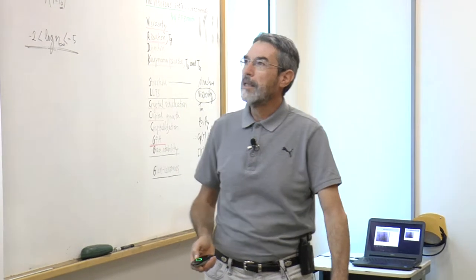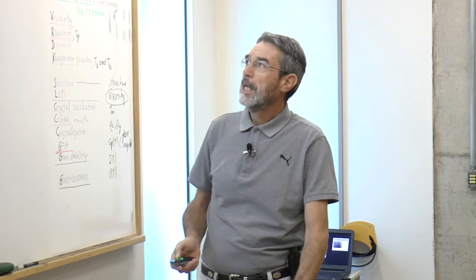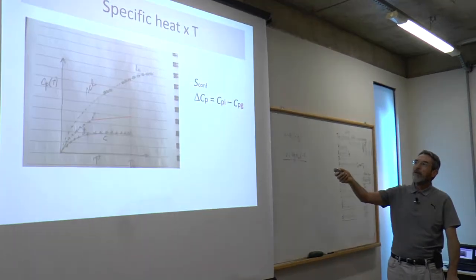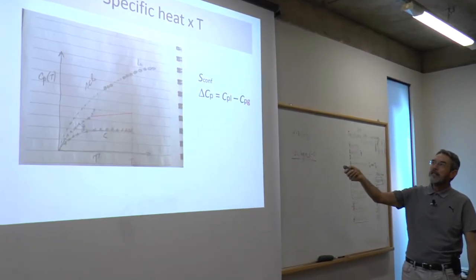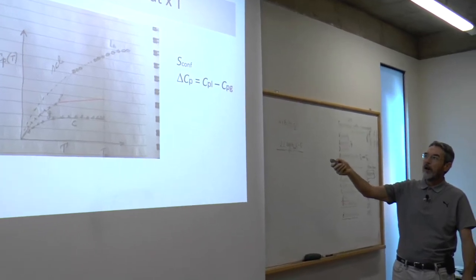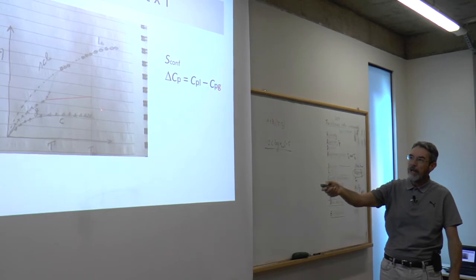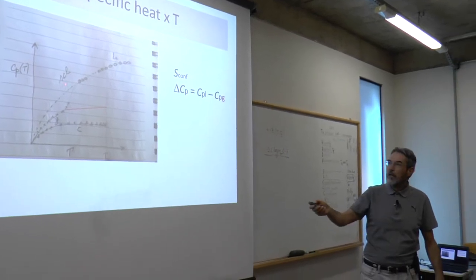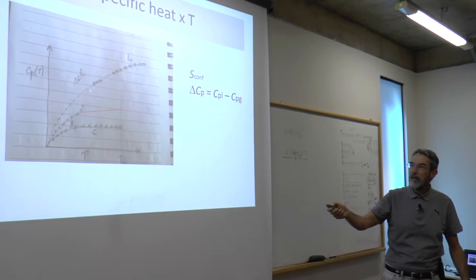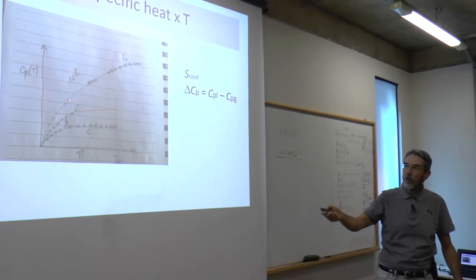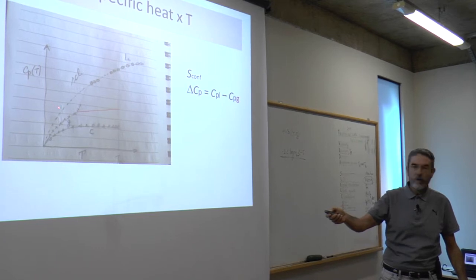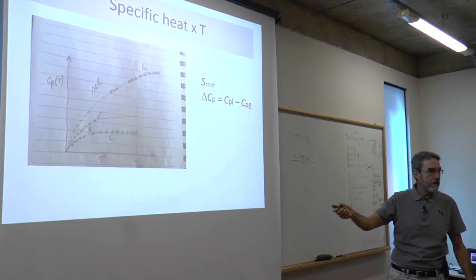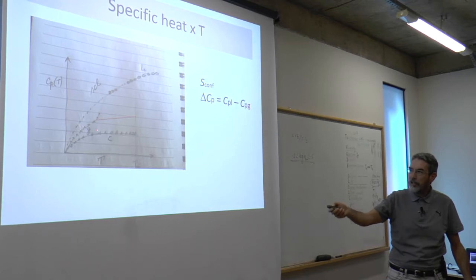Okay, I'm showing again this plot just to remind you that for the configuration entropy, we only need the Cp of the liquid minus the Cp of the glass. As we are not plotting the viscosity below Tg, we are only plotting the viscosity above Tg, we do not need to worry about this part here, okay? You only have to worry about this polynomial here and this one here, because you'll be calculating from Tg and above.